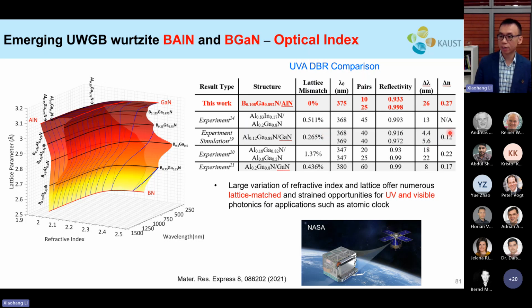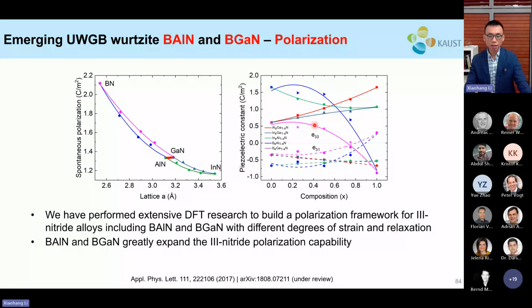Right here, for example, you have a mismatch of about 0.265% in terms of lattice, and your delta n is about 0.12. But from this graph on the left, we found that you can pick about 10% boron in BGaN, and then it is entirely lattice matched with aluminum nitride. So your lattice mismatch is zero, and in the meantime you get a large delta n, about 0.27 or so, right? So this is very promising for the future development of epitaxial DBRs for UV VCSELs. Next, I would like to talk about the polarization property of those BGaN and BAlN layers.